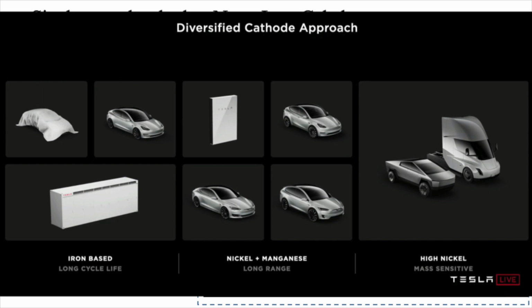They have eliminated aluminum and cobalt, and they're going with nickel and manganese. Some of this work is the contribution from Professor Jeff Dahn's group at Dalhousie, and then high nickel content. Also, they've done amazing work into high nickel content. So I'm thinking high nickel content would include novel coatings and dopants. This looks like single crystal to me. Even though there are lots of grains here, these grains could be bigger. In polycrystalline, the grain size is much smaller, whereas in the single crystal, you will still have lots of grains, but these grains will be much, much larger, like in the micron scale.